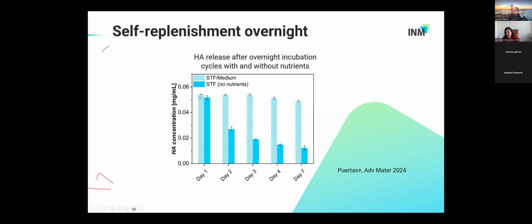It's very nice to see that if you do not feed the bacteria inside, then over consecutive days, the release of hyaluronic acid is dropping. Whereas if you feed the bacteria during the night in your simulated care solution and you measure release during the day, you can keep release more or less constant over several days. So this is encouraging because in case the feeding or nutrient conditions in the eye would not be enough, one could even do it over the day and have a reusable lens which you can self-replenish in terms of drug content overnight.